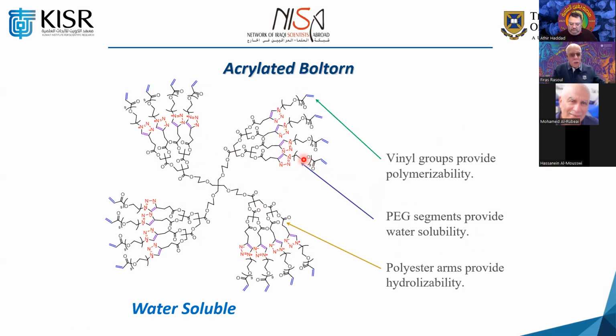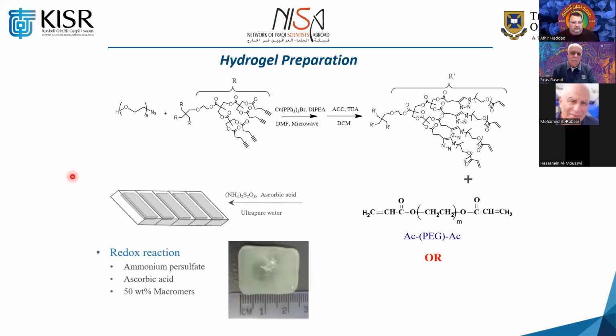We used a longer chain, we used a shorter ethylene glycol chain, but we found this one is probably ideal to convert these hydrophobic nanoparticles from insoluble in water to soluble in water. And then, of course, we functionalize it with a vinyl group to make it polymerizable. So we have a polyester arm providing the hydrolyzable component, because when hydrolyzed, it degrades. We have the vinyl group to make it polymerizable, and we have the modulation of polyethylene glycol to convert it from insoluble to soluble nanoparticles. So we use this one. This is the synthesis of it anyway.